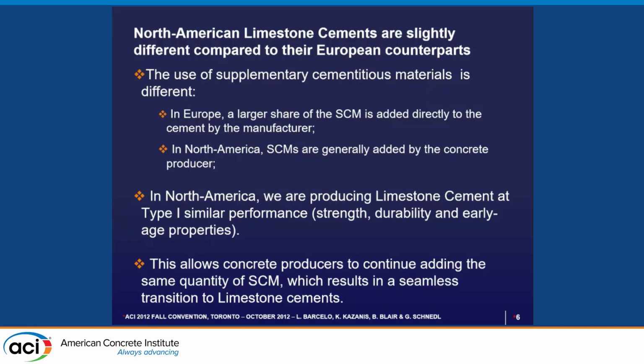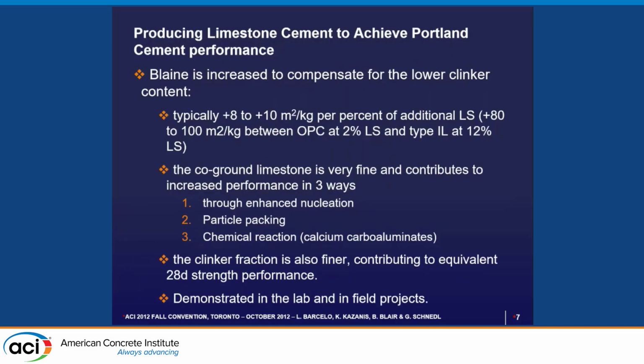And so we were looking at a limestone cement, type 1. This was a limestone cement that was produced over in Alpena, Michigan. Certainly, while they say the Blaine is increased to compensate for the lower clinker content, we're seeing that the blend today can cause a little bit of an air issue, and there can be some quality issues as well when that blend is going up and down. So you need to be aware, with the new pavements and the pavement specifications that are coming out, you need to have some consideration again for your materials.